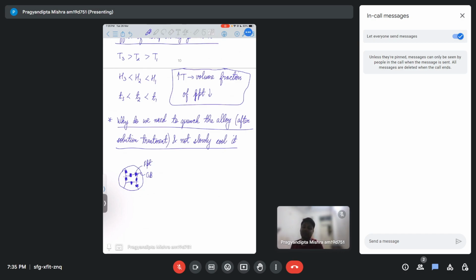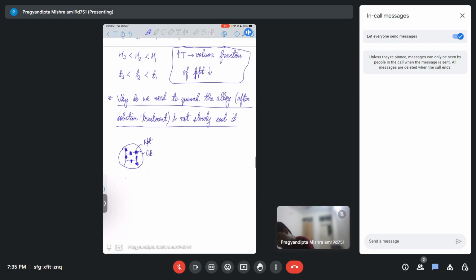Now this is bad because this is the consequence of slow cooling. Okay. Now this is bad because now most of the precipitates are concentrated in the grain boundary region, and this will weaken the alloy as a whole. Okay. So this weakens the alloy.